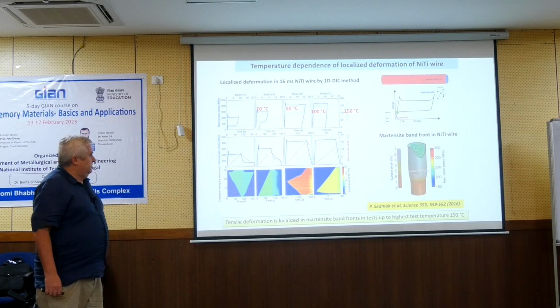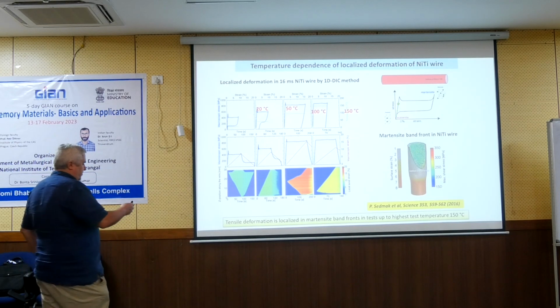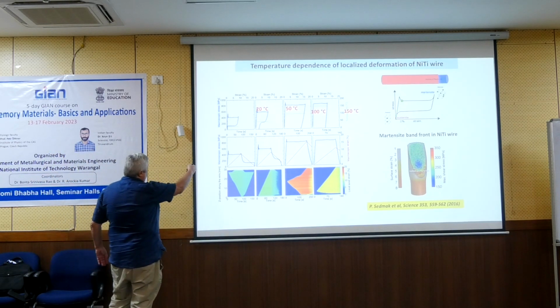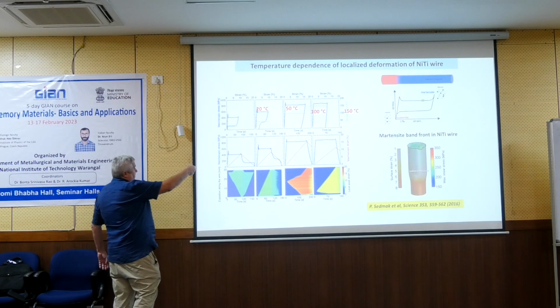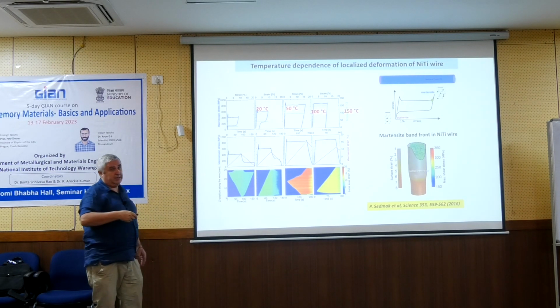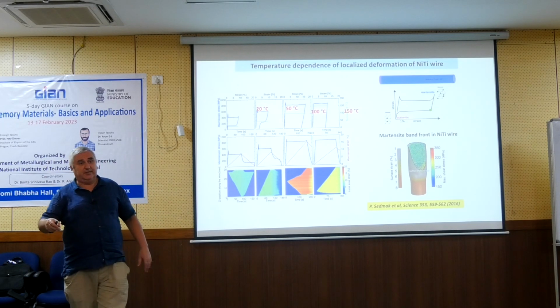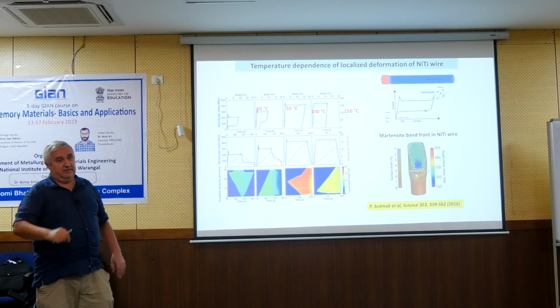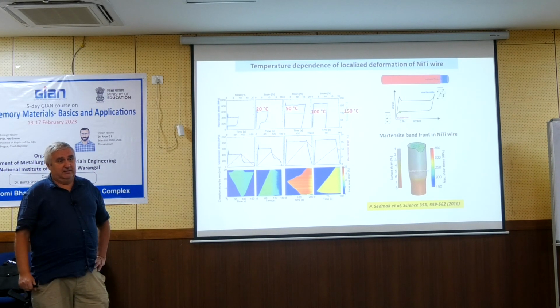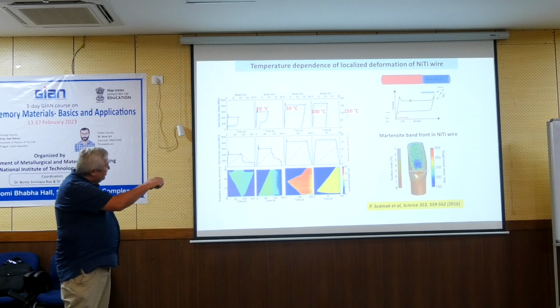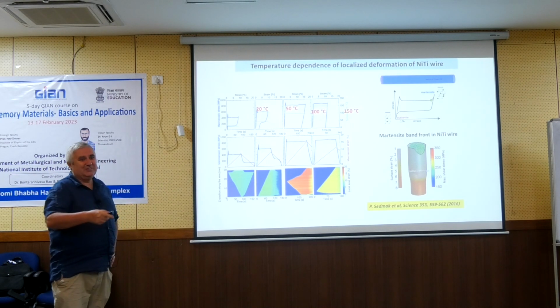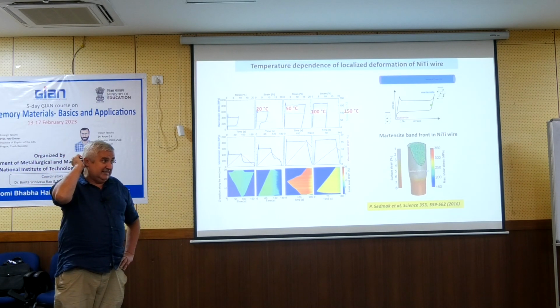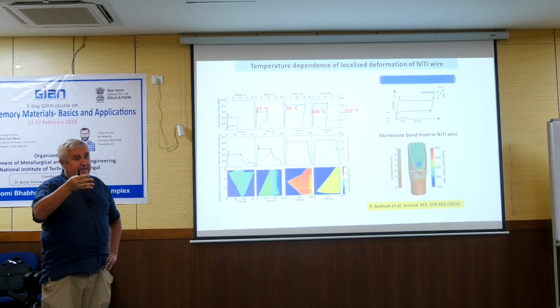And as far as I know, if you keep a constant stress in this range where only Martensitic transformation occurs, nothing will happen. You stop the test and you come 5 weeks later and it will stay constant. There is no creep in case of Martensitic transformation only. Once you go to 150 Celsius, there is some creep, but it's not viscoelasticity, due to the rate dependence, not due to the time dependence.